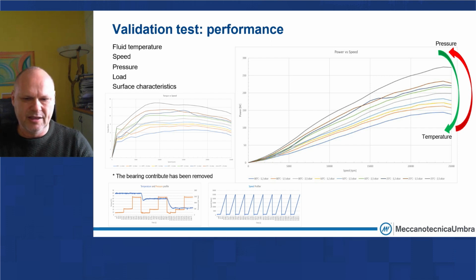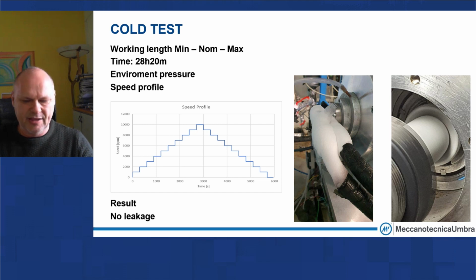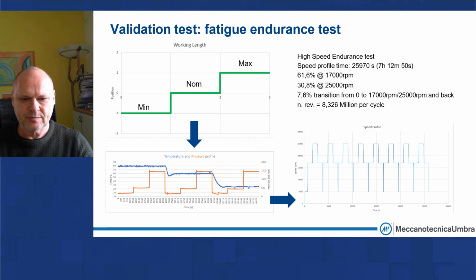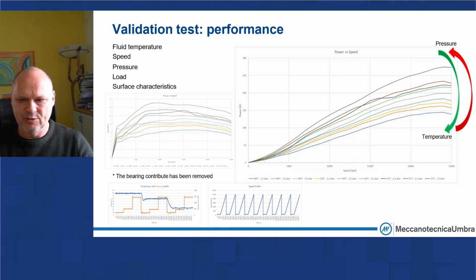What we obtain in terms of friction and power consumption is shown in this curve. So we are able to run the mechanical seal in different conditions of fluid temperature, speed, pressure, load, and we can also define some surface characteristics to have the best compromise between the power consumption and the leakage rate. We also test the mechanical seal in different temperatures, also the low temperature. And we also tested the mechanical seal for fatigue endurance test.